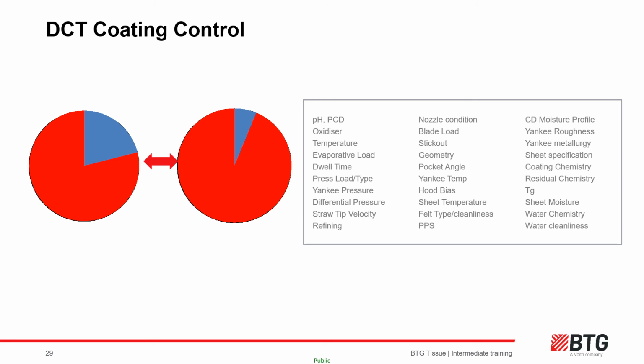Often, issues arise when 75 or 80% Yankee coating contamination factor quickly becomes 85 or 90 or 95. This could be a result of a furnish change, i.e. a higher fines containing furnish, a lower grammage with poorer natural retention, a blip in the natural or chemical induced retention mechanism, for example starches or wet strengths or even polymers added deliberately. Variable recycle from a DAF or a recovery filter could have the same effect, as could a sudden reduction in water consumption or a problem with the clarified water system.